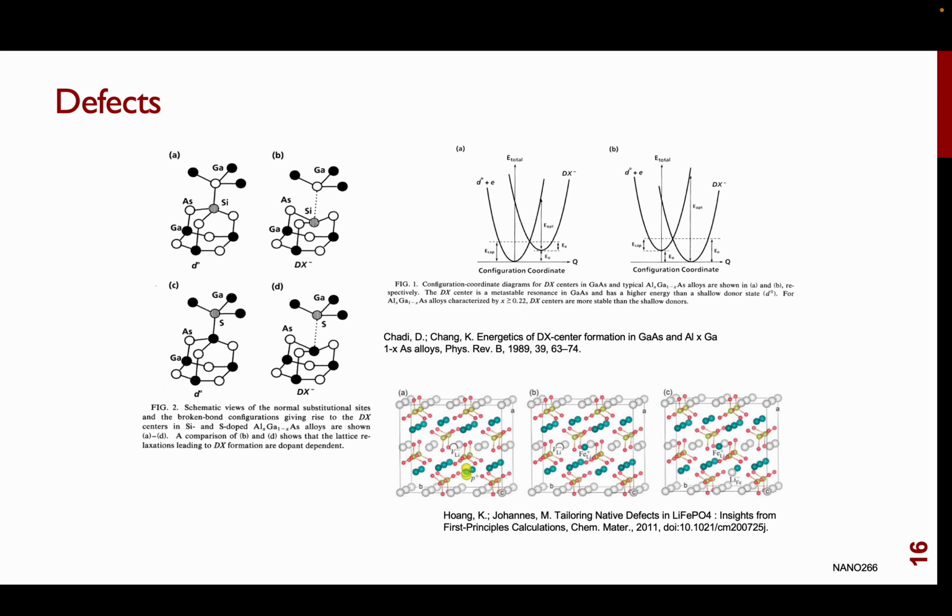People have also studied such structures in lithium-ion battery materials. For instance, I mentioned lithium iron phosphate in the DOS calculation before. One of the most interesting things about lithium iron phosphate is that, unlike most of the other battery materials out there, it is what is called a 1D ionic conductor. In other words, the lithium channels are almost like a single line of atoms. The lithium just moves along these lines.